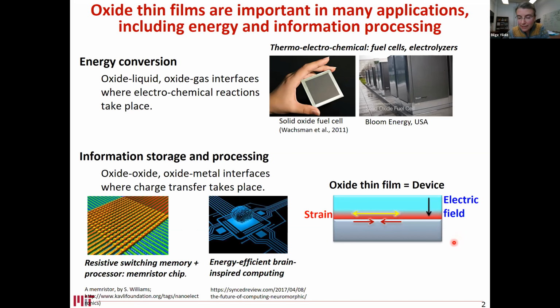Okay, so when we run into this geometry of very thin oxide films, there are additional external drivers that we ought to consider beyond the nominal composition of the oxide that we put into this application. And those are strain, in particular, strain introduced by lattice mismatch through the interface of the functional oxide with its substrate, as well as strong electric fields, because these systems run under applied voltages and across an oxide thin film, this can translate to very strong electric fields. And so what I will share with you is that both strain and strong electric fields can change the properties of the material on par with compositional engineering.